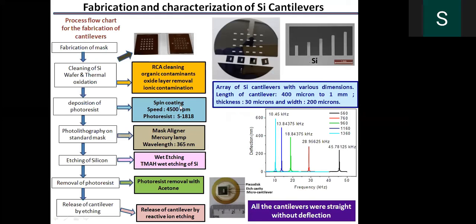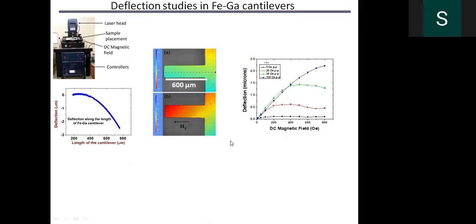We have used RCA cleaning and spin coating with the photoresist. We have used a mask aligner for defining the pattern. Then we have done wet etching, photoresist removal, and finally deep reactive ion etching was used for removing the silicon underneath, releasing the cantilever. We have deposited our magnetostrictive layer, and we try to measure the deflection. You can see this is the photograph of the cantilever before and after application of a magnetic field. Without application of a magnetic field, it is straight, and as I apply a magnetic field, there is a huge displacement, as high as 2.5 micron deflection observed in these cantilevers.